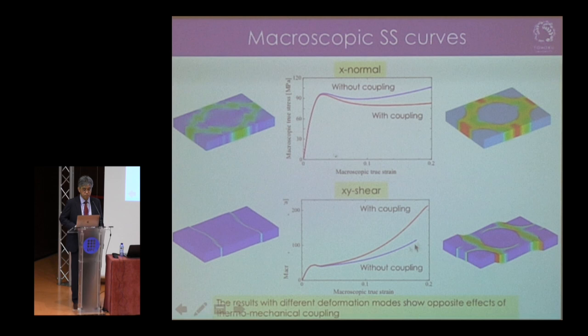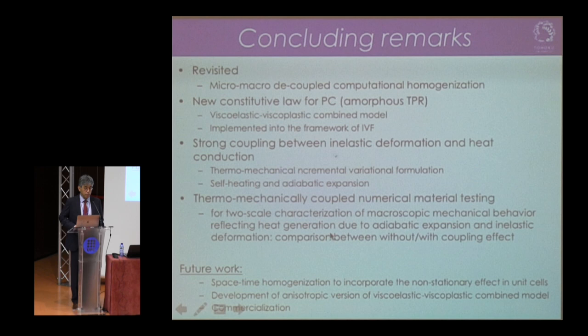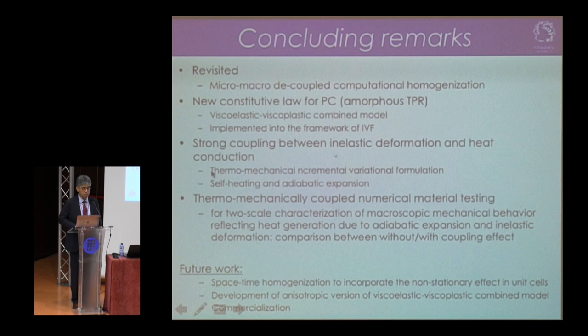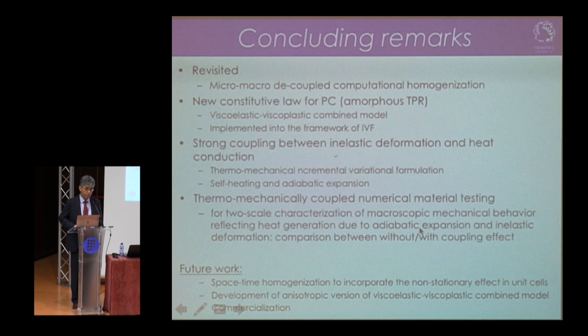In conclusion: first, with a view to applying micro-macro decoupled computational homogenization, we presented a new constitutive law for polycarbonate — a viscoelastic-viscoplastic combined model. Then, to realize strong coupling between inelastic deformation and heat conduction, we presented a thermomechanical incremental variational formulation for numerical material tests. We then presented thermomechanical numerical material tests for two-scale characterization of macroscopic material behavior, reflecting heat generation due to adiabatic effects and inelastic deformation in the unit cell. Future work includes developing space-time-type homogenization to incorporate non-stationary effects in the unit cell, and developing an anisotropic version of the viscoelastic-viscoplastic combined model. Thank you very much for your kind attention.